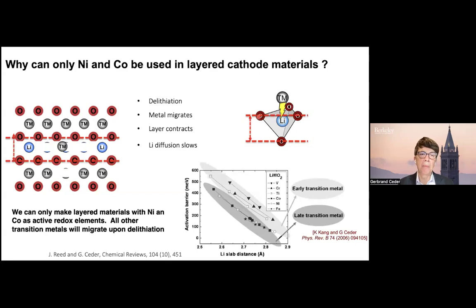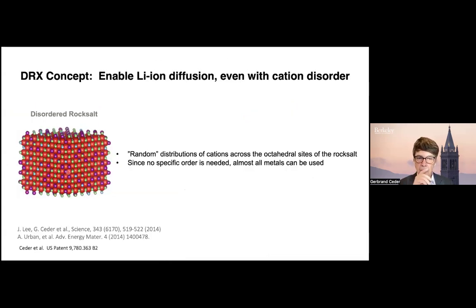So the fundamental problem is the migration of these metals. And there are only two metals that essentially don't migrate across multiple valence states, and that's nickel and cobalt. Manganese 4+ also doesn't migrate, but when you reduce it, it migrates. So 3+ and 2+ migrate. And that's really why we will only have layered materials with nickel and cobalt. So NMC, basically what you see is what you get. We're not going to do fundamentally different redox chemistry in layered materials.